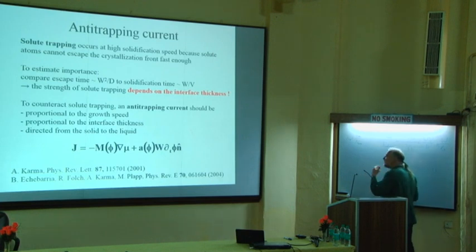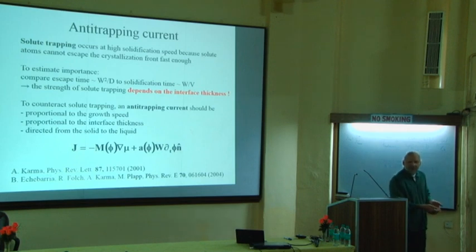So, if I say the equilibration of the two sides of the interface doesn't take place, that means there is a chemical potential jump between the two sides of the interface in real systems if I go fast enough. So this has been well documented, has been measured in experiments. There have been models for this which contain this small parameter. So it's a physical effect.